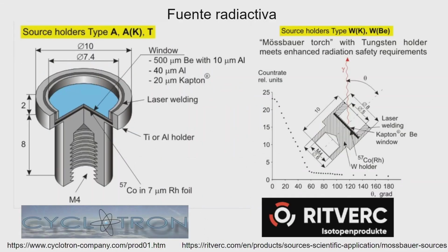Well, this is a typical Mössbauer source. It's a very thin layer of rhodium with cobalt-57 in it, usually covered with some kind of protection which should not absorb sensibly the radiation. So it could be kapton, it could be aluminum also, it might be very thin, or sometimes beryllium. Beryllium is very much used, and kapton, okay?